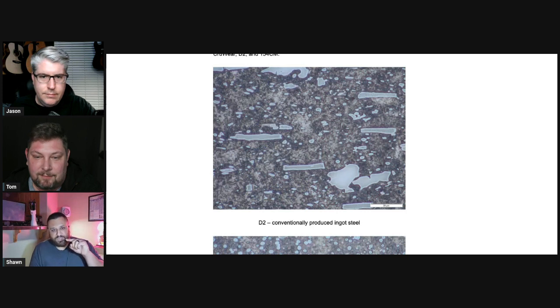So these white features right here, that's all you should be focusing on when you're looking at this micrograph. You shouldn't be looking at the busyness and fuzziness of the background, because that's not what we're trying to highlight with this particular etch. We're burning down the matrix and we're trying to look at these carbides here. And these white features are actually gigantic. This is D2 chromium carbides.